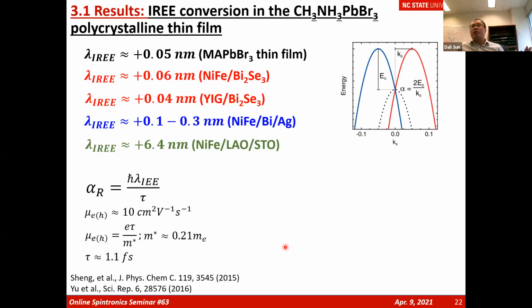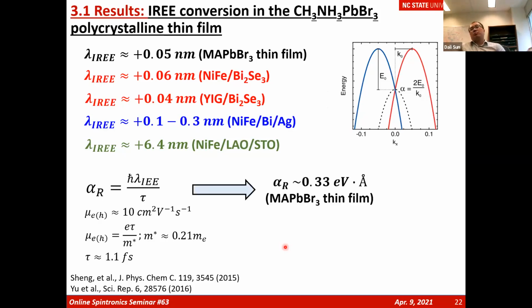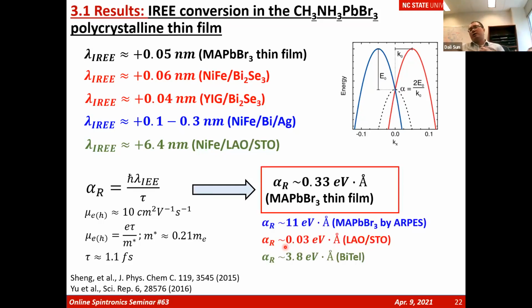But if we calculate the Rashba parameters using the effective mass and mobility from these materials, the Rashba parameter in a polycrystalline thin film is 0.3 eV·Å. It's not huge, but decent. It is still orders of magnitude lower than what was observed before, which is 11 eV·Å. Even though it's lower, it's still larger than LAO/STO.